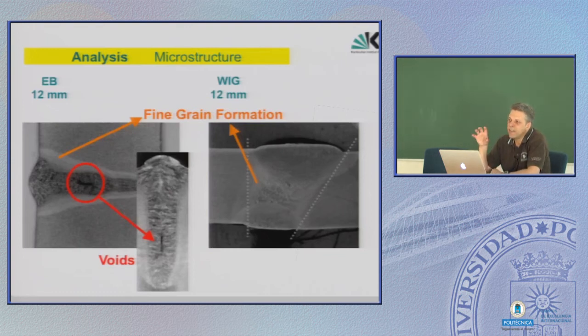So the cooling rates after welding or during welding are also very important for beam welding. It's completely different for tungsten inert gas welding, because here you control the joining layer by layer. The drawback here is that the dimensions of the weld are really huge. They can be several centimeters in the end, depending on the dimension you are doing this.